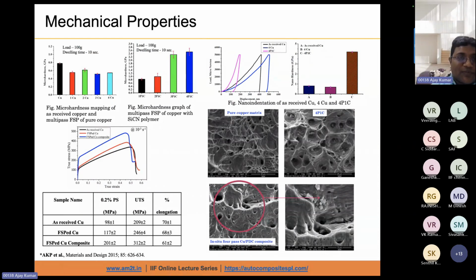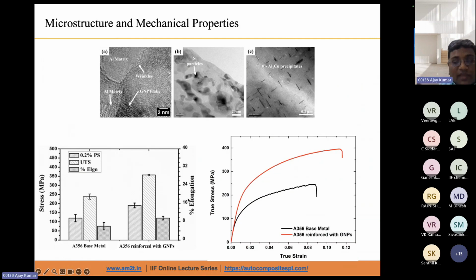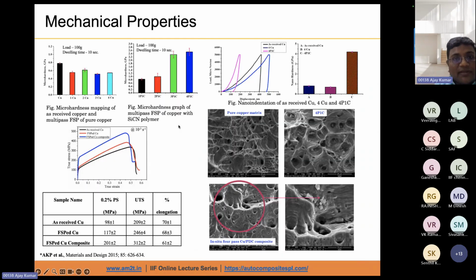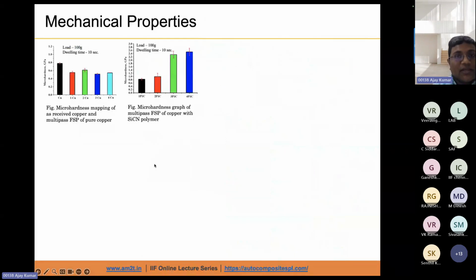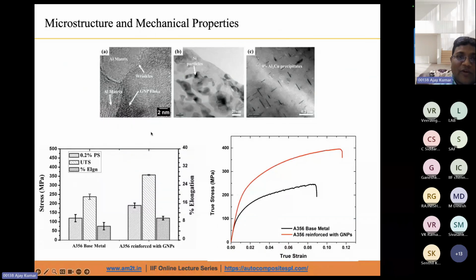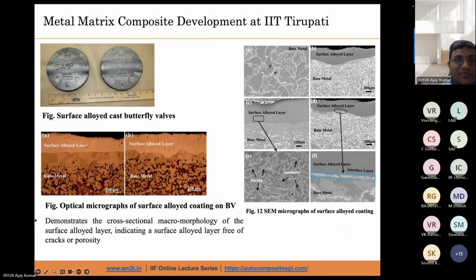Individual processes may not help sometimes, but if we can come up with a hybrid approach, we can address a lot of challenges. So here we have developed copper based composite materials. These results are for copper based composite materials, where we have used polymer derived ceramics as a reinforcement. And here is the example of aluminum based composites, where we have reinforced with graphene nanoplatelets. This is the true stress strain curve for the matrix material, and then this is the composite material. So you can see significant improvement in the properties.